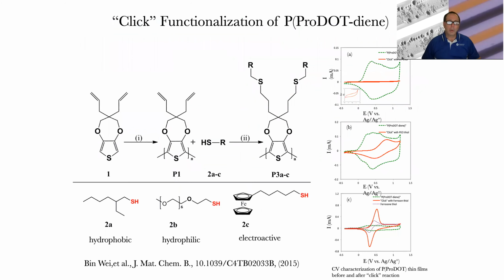So this was some work by a subsequent graduate student, Bin Wei, where he had the difunctionalized ProDOT, and he used different thiols, one being hydrophobic, which shut down the charge, one hydrophilic, which created a nice wet surface and essentially didn't change the charge transport much at all, and then one that had an electroactive ferrocene and really caused a lot of electrical activity that we could easily see when we did CV.